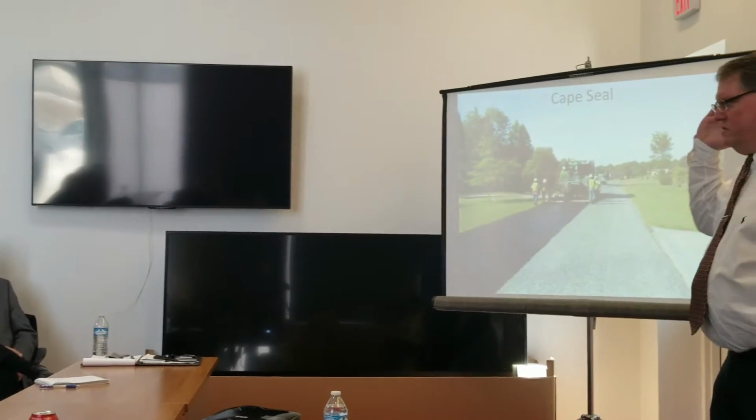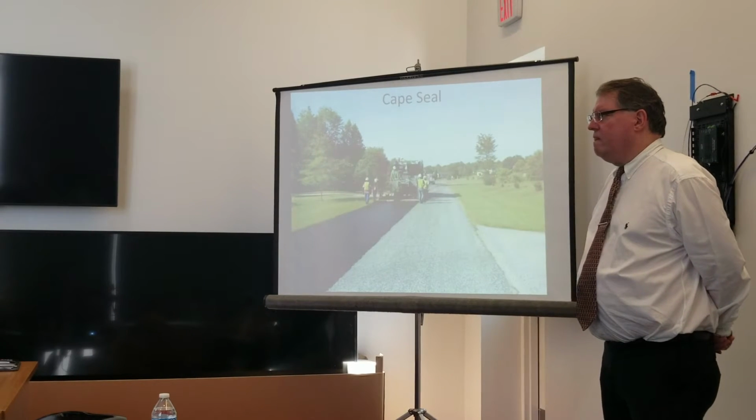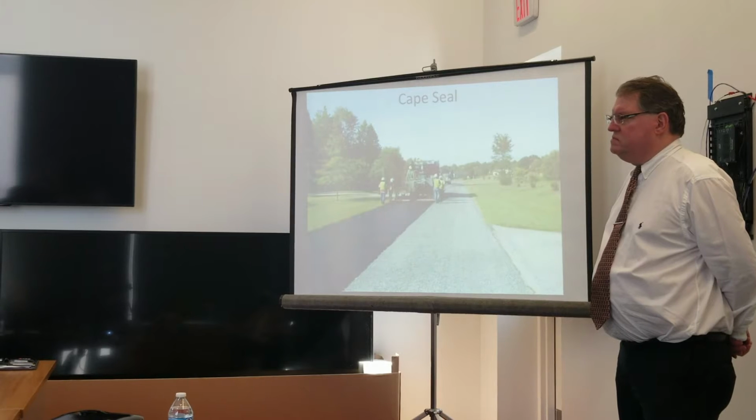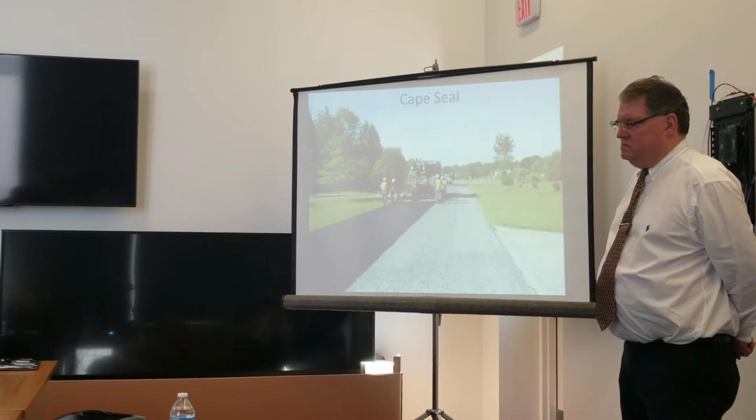An effect of that road drying out are cracks. And usually the first ones are transverse cracks across the road. And then I know that a year from now, if I have two transverse cracks that are 30 feet apart, I'm going to have another one at 15. It's going to be in the middle of that. And then it's going to be in the middle of those two, so I can kind of see that.